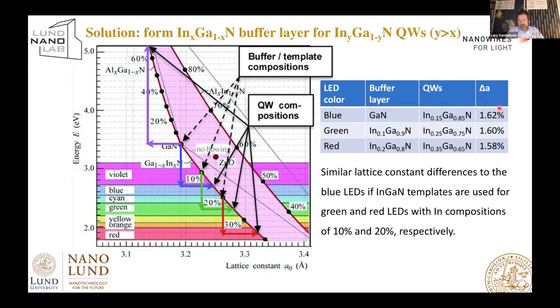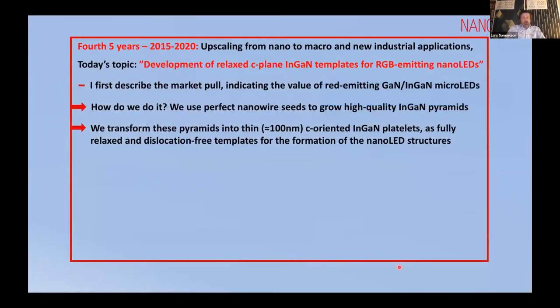For the blue, you have on gallium nitride 1.6% lattice mismatch. For the green on 10% indium, 1.6. And for the red on 20% indium, 1.6. All seems very easy. It's just to go out and do it. It's not perfectly trivial, but that's what we've been doing. So how do we do this?